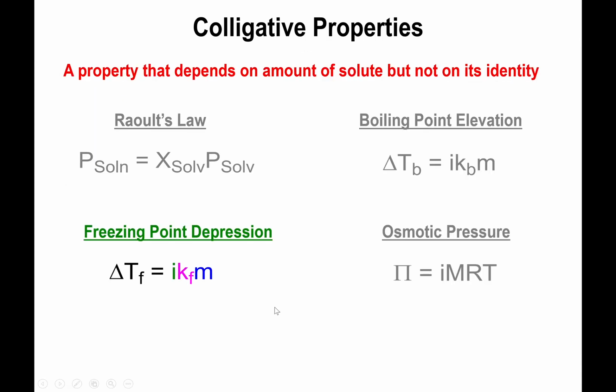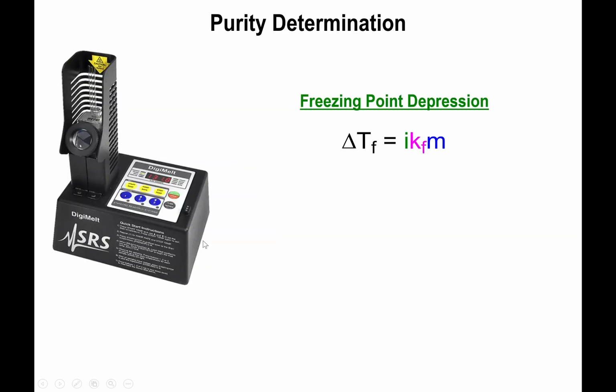And the other thing is that with melting points, you can assess the purity of your sample. In particular, we can exploit the colligative property of freezing point depression, because having even a 1% impurity can drop the true melting point by about 0.5 degrees Celsius. So it's actually very decent. And if you have a greater amount of impurities, you will decrease the melting point even more.